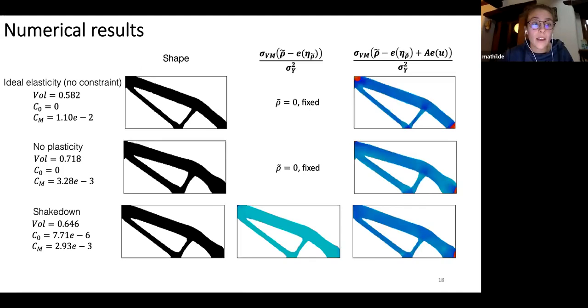And now I go to the results. So that's the same test case as the first one I've presented before. We run it only on half of the domain. We pull here and we fix here. And on the first line, we don't consider any constraints. So we don't care if there is plastification. We only minimize the volume plus compliance. And of course, the volume is the smallest because we don't constrain the problem. But we have plastification here, here, and here.